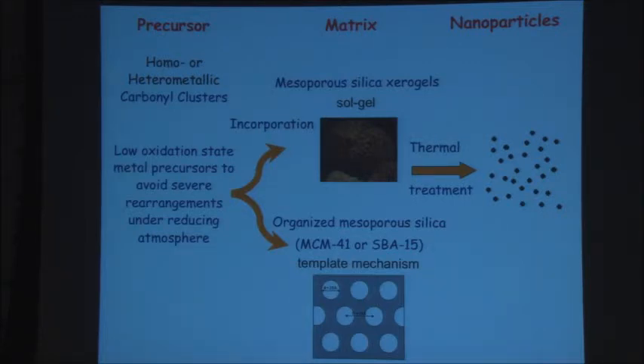You can use different matrices to impregnate your cluster. You can use mesoporous silica xerogels prepared by the sol-gel method, or organized mesoporous silicas like MCM41, SBA15, which have a porous structure. And the idea is, can we put the clusters into the pores and have, in addition, a confinement effect due to the size of the pores? And after thermal treatment, obtain metal particles that will be analyzed by various methods.